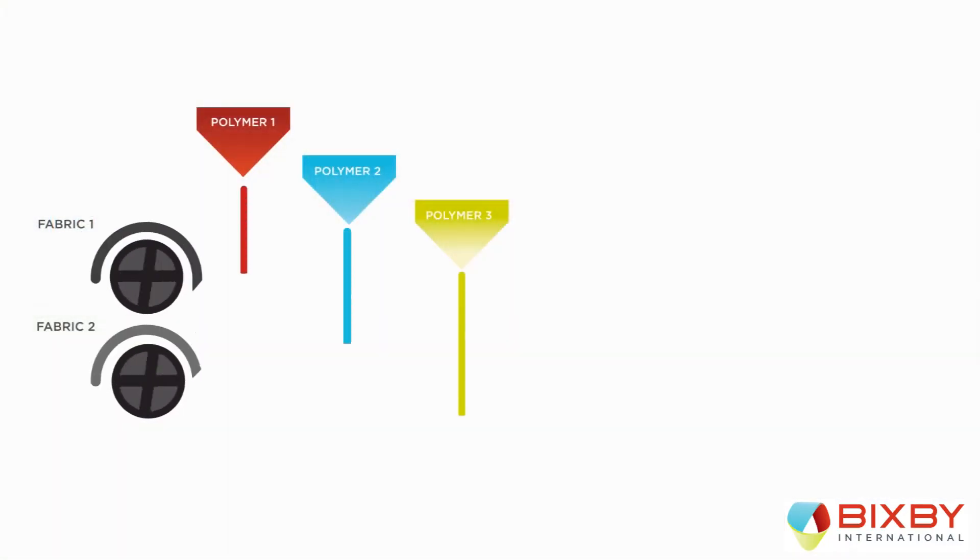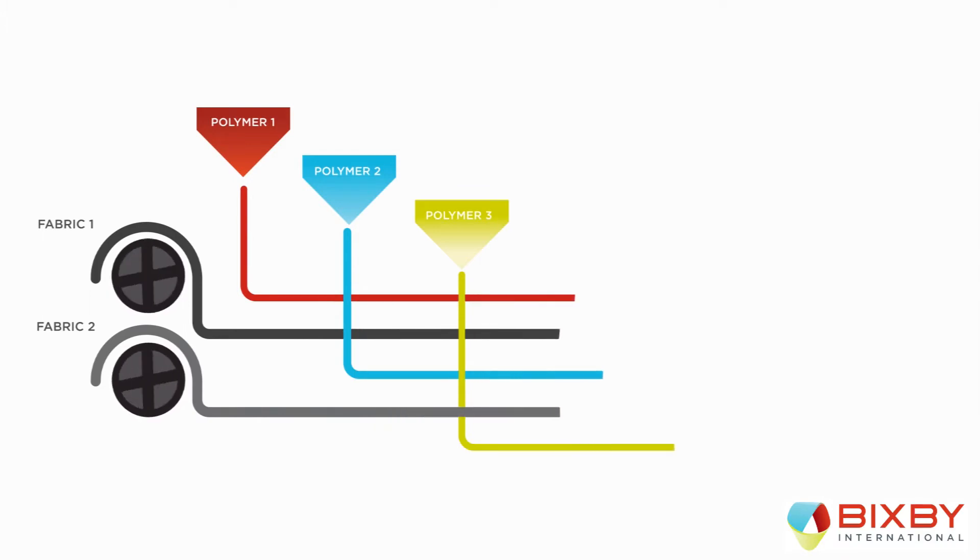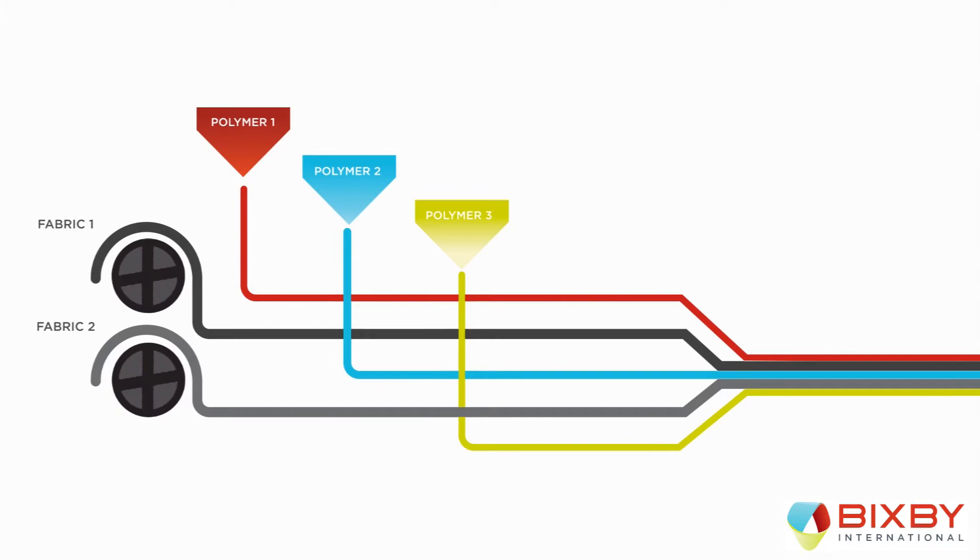This is achieved by extruding molten polymers between functional layers, whether that's foam, reinforcement, or an extruded web. If any functional layers are found to be incompatible — for example, if the foam isn't bonding well to the extruded substrate — Bixby can modify the tie layer chemistry by combining different compounds or additives to make that tie layer compatible to both the superstrate and substrate. Additionally, you can surface-treat any of the superstrates or substrates — for instance, corona treating foam to increase surface energy. You can also use primers, coating a primer onto one surface to make it more compatible with the tie layer or directly extrudable with a functional layer such as a urethane or polyamide. This is crucial because getting good wet-out is critical to ensuring a good, long-term durable bond.